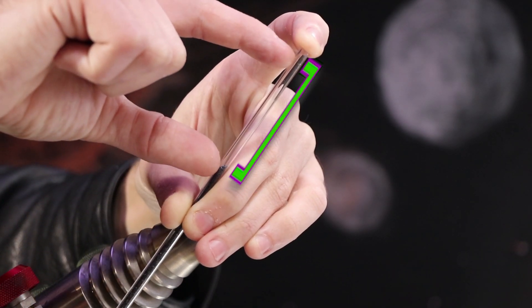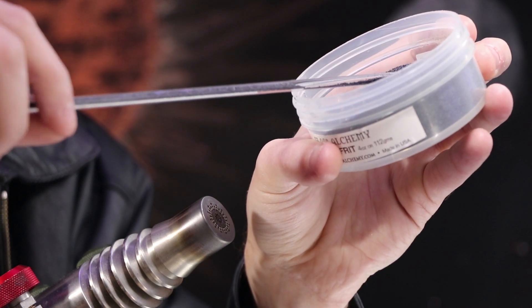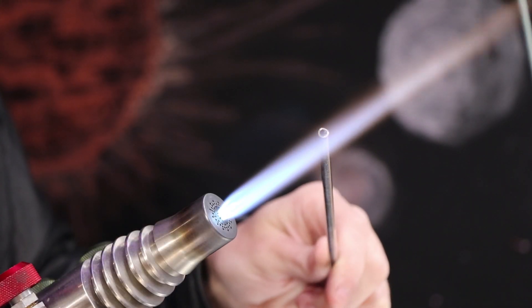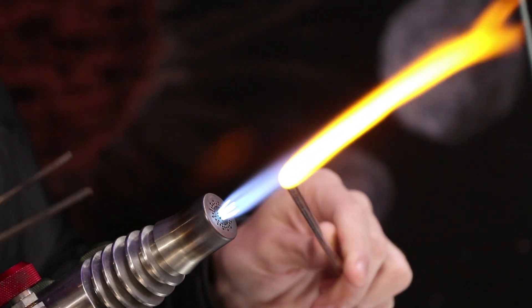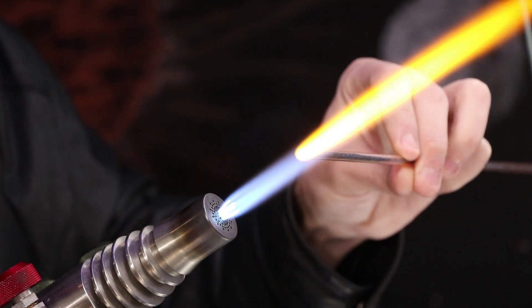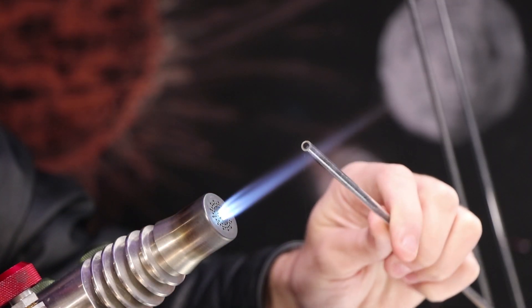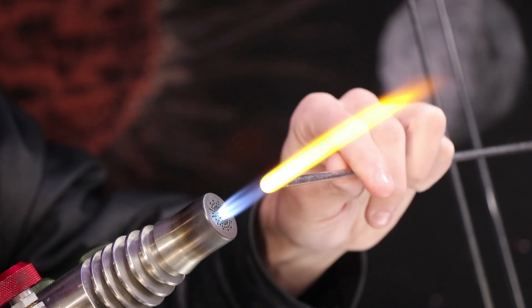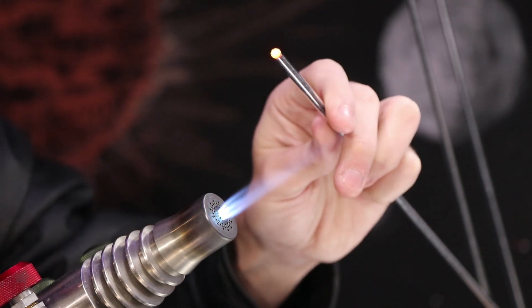Since I'm going to seal the tube up, it would eventually end up with a huge space as the frit settles down over time. I'm going to fill up the rest of that gap and keep tapping it down until it's completely full. Even though I've done this method quite a few times, you don't really want to seal up things with air inside — any hollow work with tubes. That inside air might contract or expand, causing a negative or positive pressure and maybe blow up your piece. For something like an hourglass or sand timer, you'd want to wait until it's cool, fill it up with sand, and then glue it closed. My sand timer is actually pretty accurate — 28 seconds. I filtered the dust out of the frit and even evaporated the water in the kiln, so it runs real smooth every time.